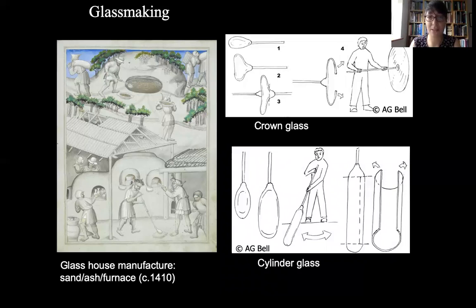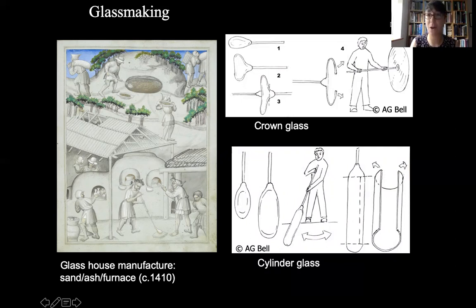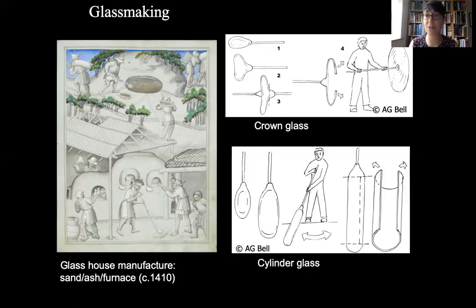The stained glass artist will actually purchase the raw glass material from the glass blower, so the glass blowing takes place separately. I often get asked how sheet glass is blown, and I hope this slide demonstrates a couple of those techniques. The glass blower picks up the molten gather of glass on his rod - glass being heated sand and ash to a very high temperature - and with the glass blower's rod he can blow and spin the pipe to get crown glass, which uses centrifugal force spinning the glass into a spun disc called a crown disc.